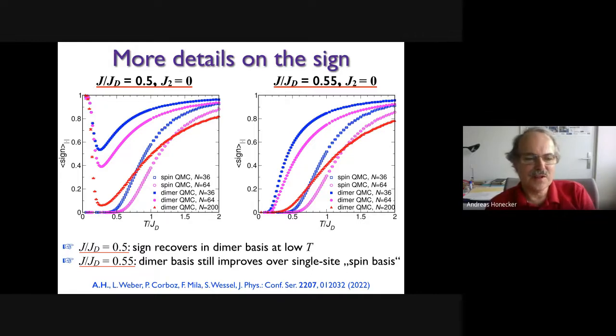In the single spin basis, you always see that the average sign goes exponentially to 0 as you go to low temperatures, and that gets worse if you go to bigger systems. So if you go from 36 to 64 spins, you basically can't do anything below a temperature of 0.5. At the ratio of 0.5 in the left case, this is cured by the dimer basis for effectively up to 200 spins. On the right-hand side, the dimer basis doesn't cure that completely. It also goes to 0.